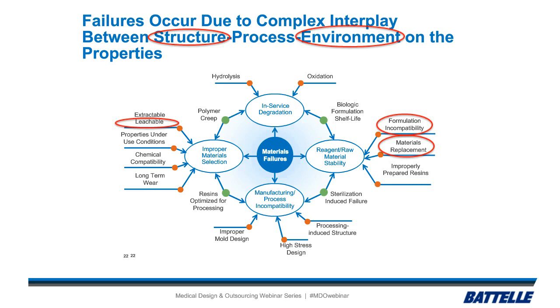This one was structure. So the structure was a crystalline ionophore instead of in solution. And the environment, for this one I'm calling the environment the close proximity of the hydrogel with the PVC, and then getting the leachable out of that PVC, the plasticizer, into the hydrogel. So it was a formulation incompatibility, and the material replacement is what started all of this. So a structure and an environment on that one.